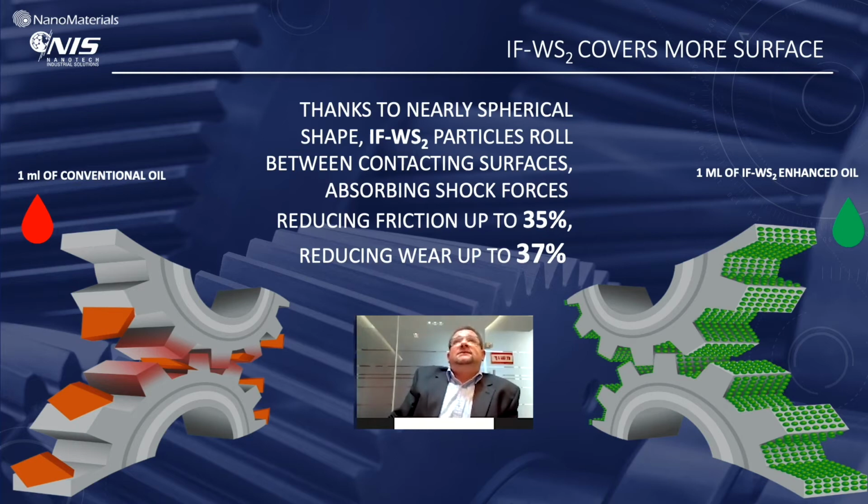The small size gives another remarkable feature: a low dosage of those materials is sufficient to reach the desired effectiveness, which is unbeatable with other analogs. Many researchers showed that friction and wear between contacting surfaces may be reduced by up to 35–40%, depending on the particular application.